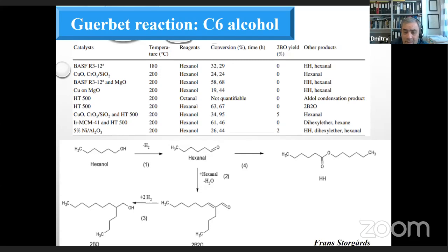Here we tested quite a lot of catalysts, as we can see here, based on copper, nickel, and iridium. Even more catalysts were tested, as I will show you after a while. And for the reaction to occur, we had to increase the temperature a little bit compared to C4, C5 alcohols.